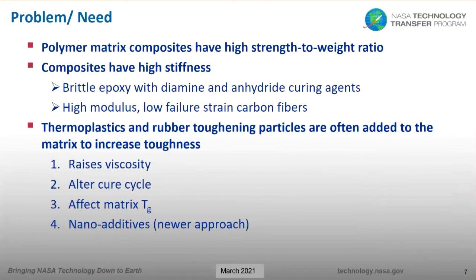So polymer matrix composites are replacing metals in more and more applications because of their high strength to weight ratio. But one issue with aerospace grade carbon fiber composites is their stiffness. The high stiffness is due to the carbon fibers and also the brittleness of the thermoset resins that are often used. To introduce more toughness, a common approach is to add thermoplastics or rubber toughening particles to the matrix. But introducing additives to the matrix raises the resin viscosity, which is something you always try to avoid when processing composites.